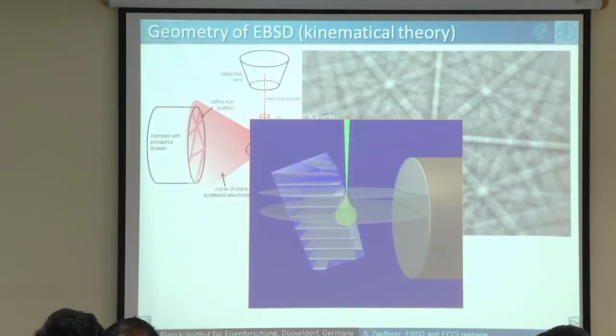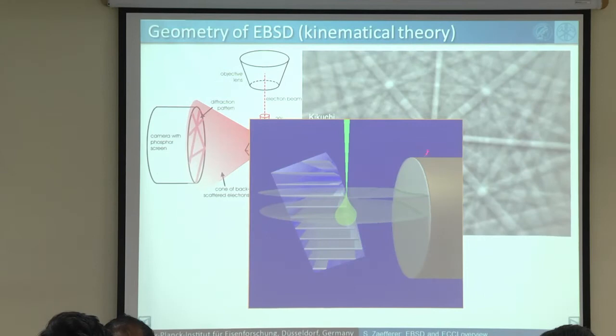And actually, what you see here, these cones, I mentioned these cones are traveling under the Bragg angle, and in electron diffraction, the Bragg angle is very small. The Bragg angle is only in the order of 1 degree or 2. So these cones here are almost perfectly flat. They have almost no opening angle. It's almost a flat plane, and that's why when you place a detector here, you will find that these cones here are almost making straight lines. They are not really straight lines. They are slightly curved because it's cones which are cutting the detector, but almost straight lines.